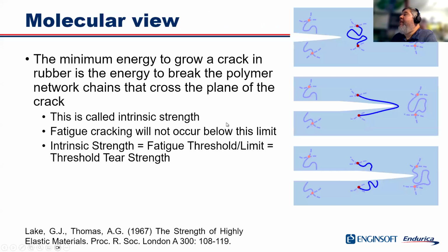So as a crack approaches a polymer chain, the polymer chain stretches out. In the measurements that I'm going to show you, we're going to use an experimental method that uses cutting with a blade to measure the intrinsic strength. That's what you're seeing in this image here. We have a blade, it's penetrating into the rubber, and we load up the polymer chain and break it, and that's how we're measuring the intrinsic strength, right? So T naught is the intrinsic strength, and that's what we need to measure. And of course, if you're operating at energy below T naught, there is no crack growth.